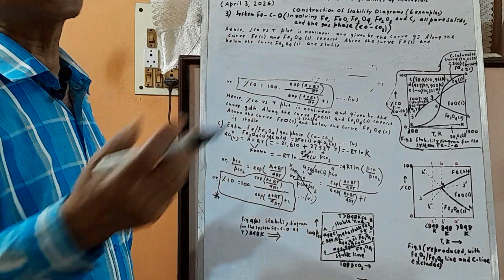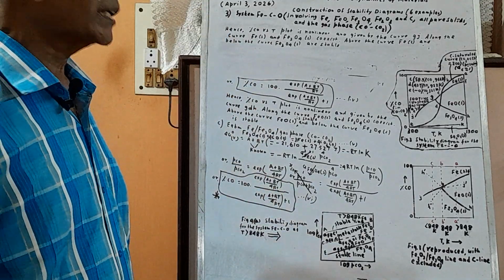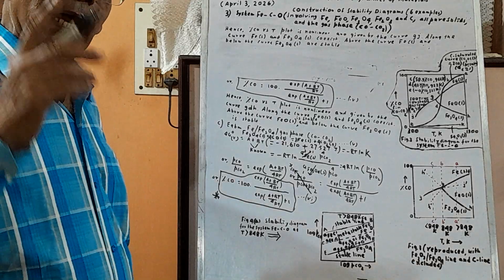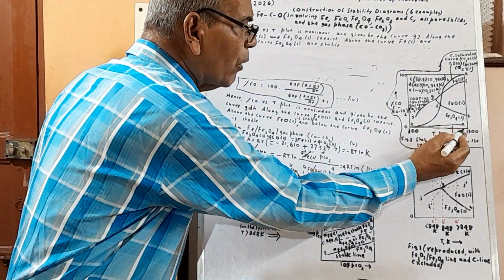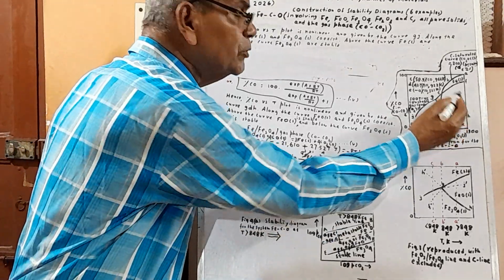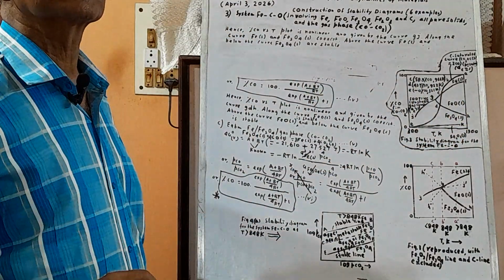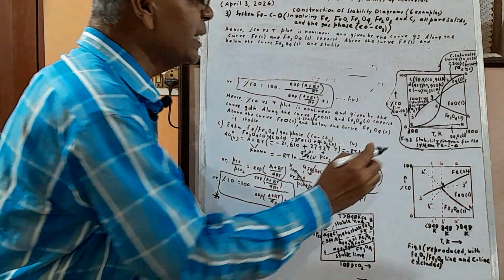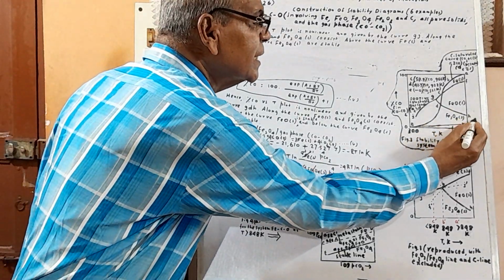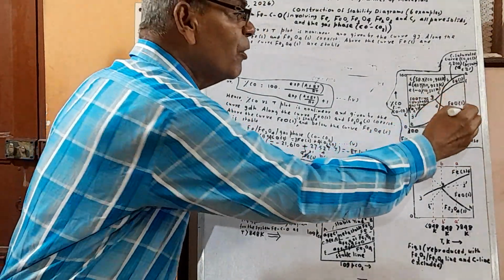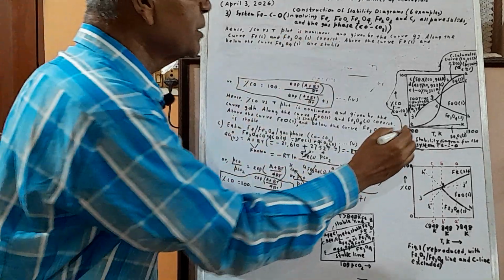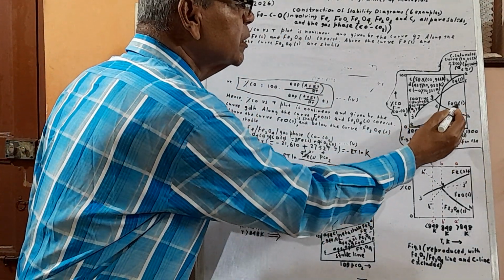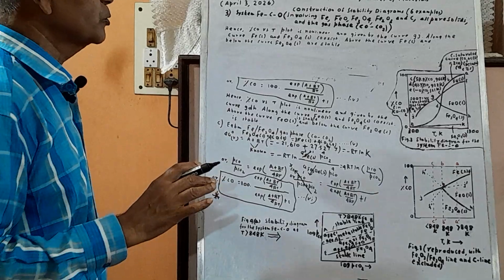Why is Fe2O3 asked? And an even more intelligent student will ask, sir, then why is the Fe2O3 and FeO line? Then the teacher will explain that if we extend this, they will intersect, and that point is the triple point for the three phases Fe2O3, Fe3O4, FeO. So don't worry about so many things, okay?